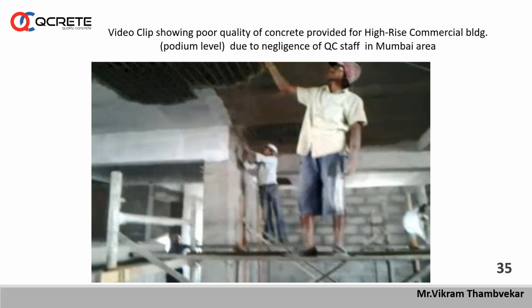So instead of using it directly, you should cast the cubes. Then either you can reject the material, or cast the cubes and then ensure whether this proportion was good. Or make a small ball of this fresh concrete with hand packing only and throw it upwards up to say 1 or 2 meters. Then let the entire ball come down with the same cohesion. This is a very primary thumb rule to test the cohesiveness of the concrete, or whether the fresh concrete is segregated. So this tactic can be used to check the fresh concrete and its cohesiveness.